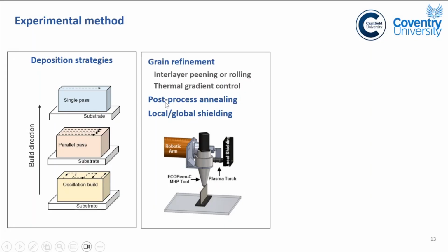So then they also tried post-process annealing, to anneal the material above the beta transus temperature for titanium, to introduce beneficial lamellar large colony structures. I will talk about this. Then they also studied the global versus local shielding.